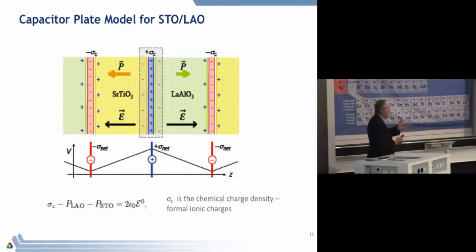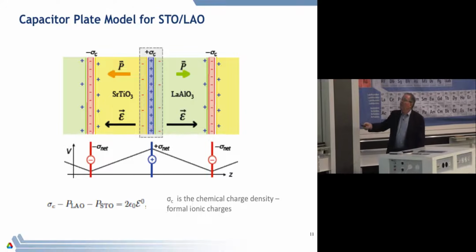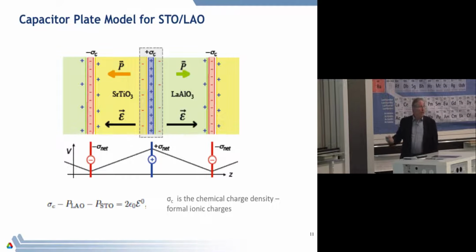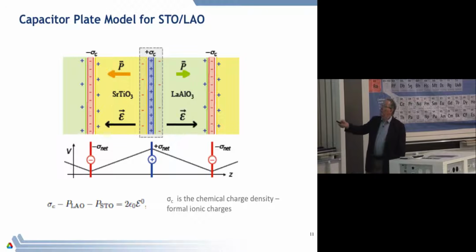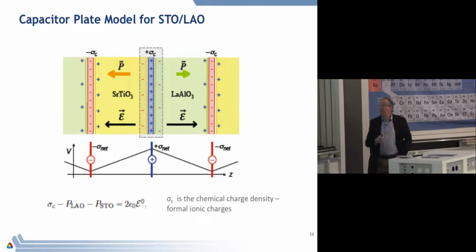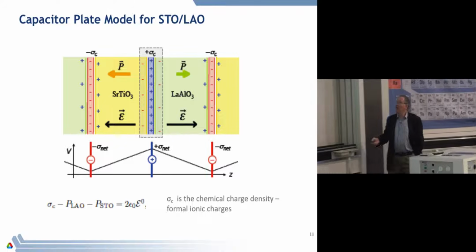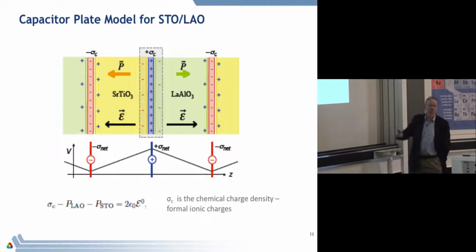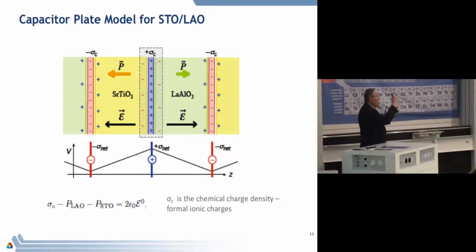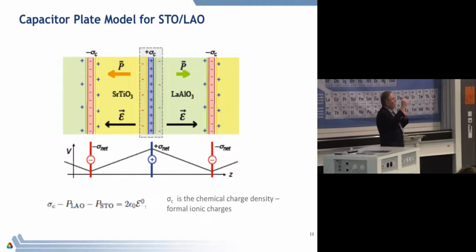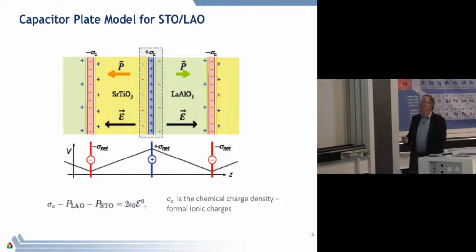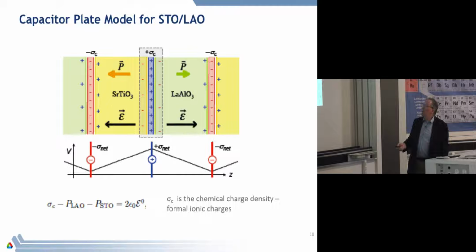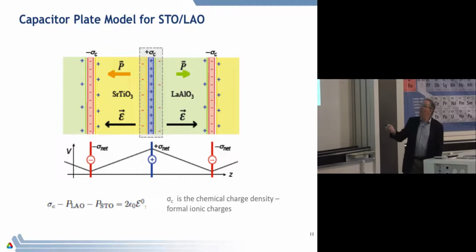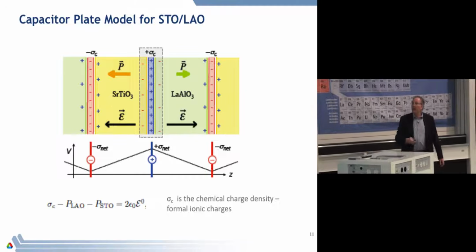But of course, those charges are just fixed. But if I now have a potential in here and I start sprinkling electrons and holes around, they will flow to screen the charges on these plates. And notice also, by the way, that if the voltage difference between these two things begins to exceed the band gap of the materials, then once this voltage exceeds the band gap, then in fact you will begin to deplete carriers from one material and have electrons flow from one side to the other so that they can be built up one way or the other. Okay?